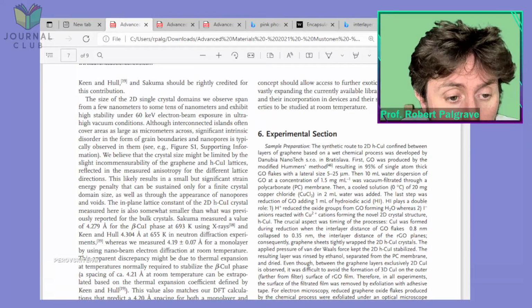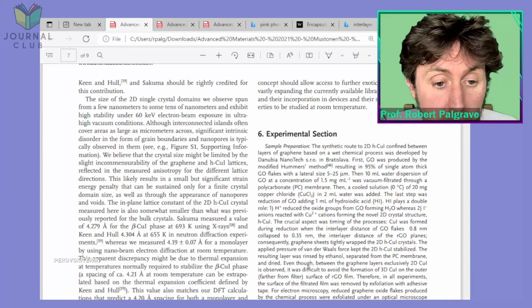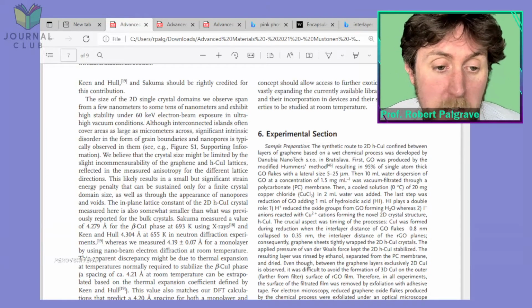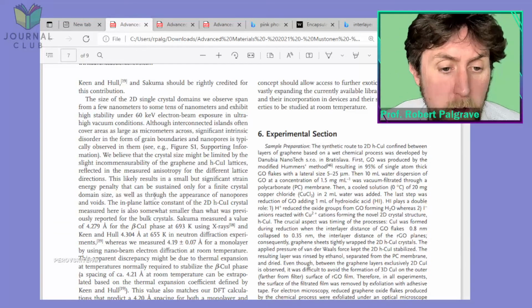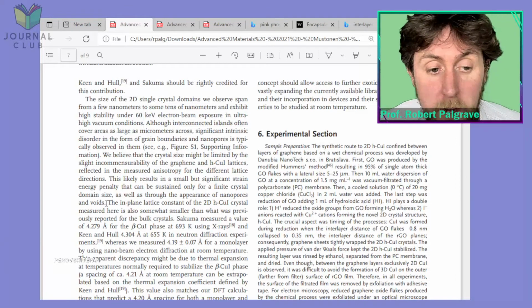This likely results in a small but significant strain energy penalty that can be sustained only for a finite crystal domain size, as well as through the appearance of nanopores and voids. There we go, that's kind of what I said.